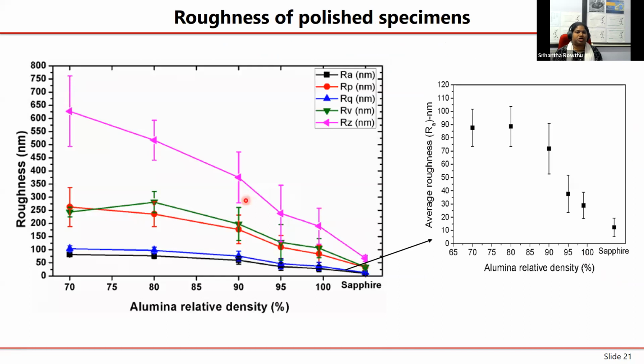After polishing, if you look at the roughness, you can see that different roughness parameters are plotted: Ra, Rp, Rq, Rz, etc. And you see that with increase in density of the samples, your roughness has decreased, which is obvious because when you have lower density, the grains, which are like spherical balls, have minimum contact between them. If this is the contact, definitely there is this sort of roughness. But if the contact is very high and atoms are diffusing during the sintering process, it tends to remove the curvatures and makes the surface flatter. That is why your roughness decreases with increase in density.